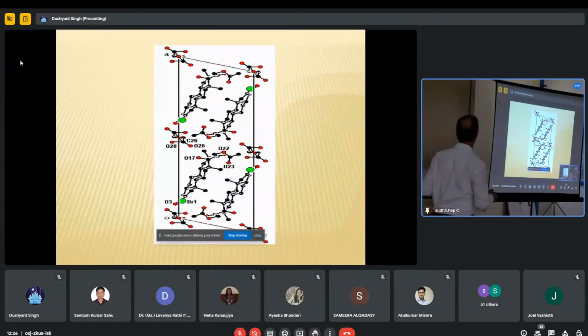Sir, hardly 2 minutes. Because the whole molecule is showing one occupancy, your solvent is showing 50% occupancy because it is sitting on the two-fold axis. 50% belongs to this unit cell, 50% belongs to the other unit cell. So two-fold rotation symmetry is present in the acetic acid solvent only.